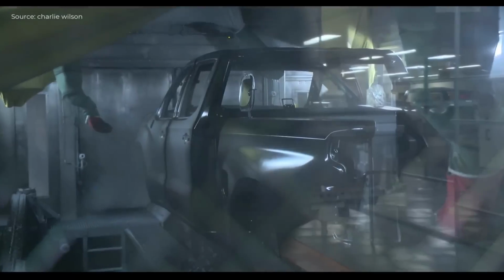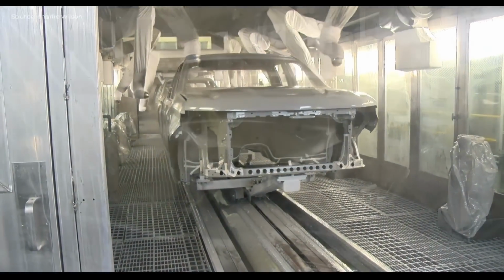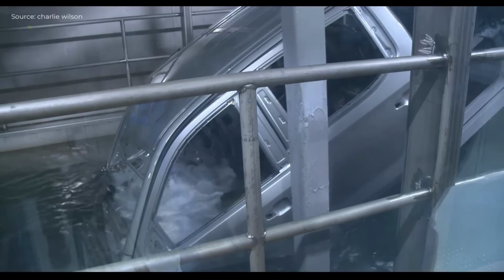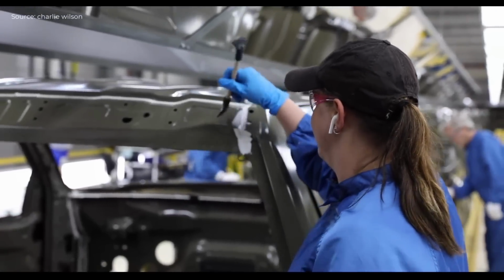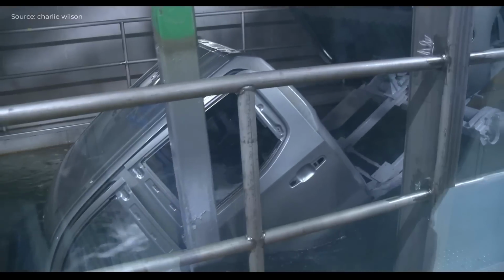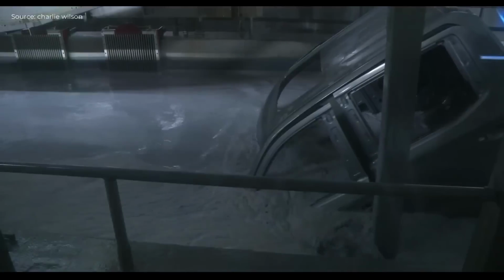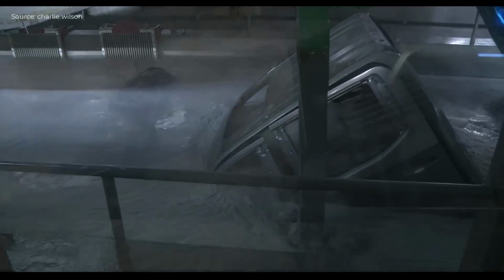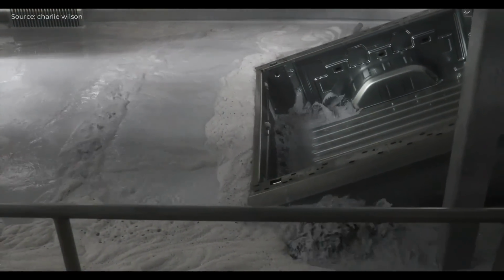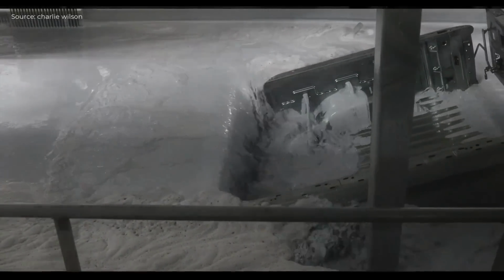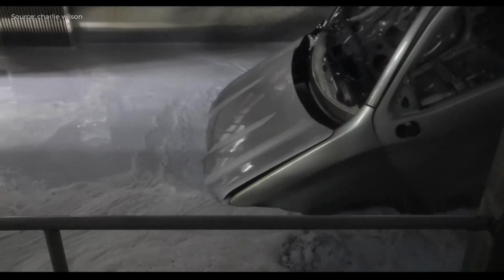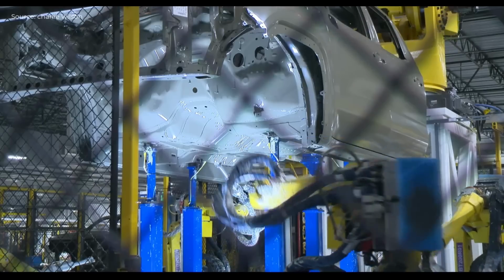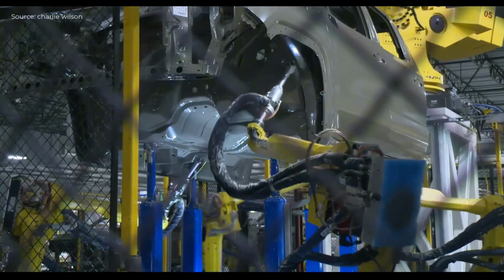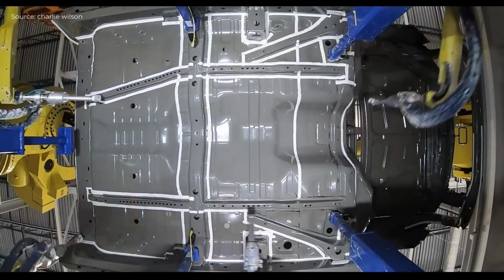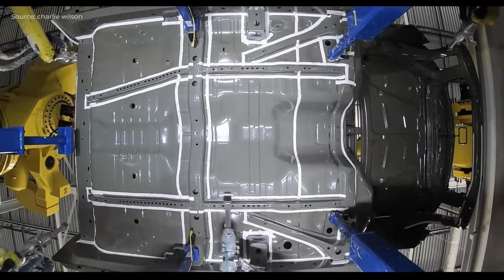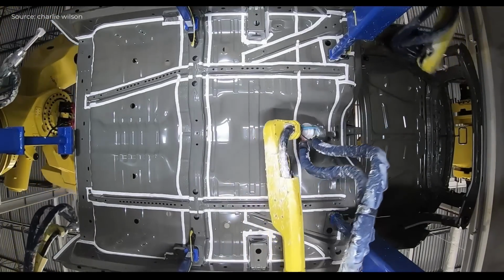Welded truck bodies from the body shop are first cleaned, rinsed, and immersed in a zirconium pre-treatment bath to clean and etch the metal surface. After a second rinse, an electrodeposition e-coat primer is applied using a cathodic process to prevent rust and corrosion. The e-coated bodies are then baked in an oven to ensure complete coverage and durability. Following a manual inspection, robotic sealing operations are performed to make all seams watertight, and liquid-applied sound deadener is added for a quieter ride.